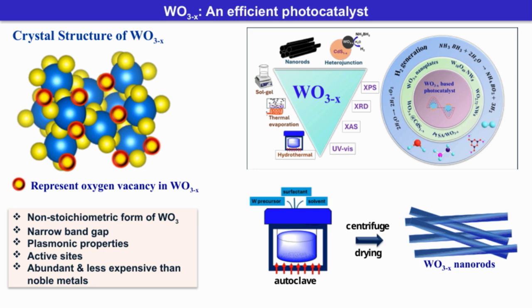choice for large-scale applications. These oxygen vacancies, often represented as WO3-x, are fundamental because they modify the crystal structure and electronic properties, essentially creating more active sites and improving performance. Looking at the crystal structure of WO3-x, we see how these vacancies are integrated into the lattice, which plays a crucial role in its photocatalytic behavior.